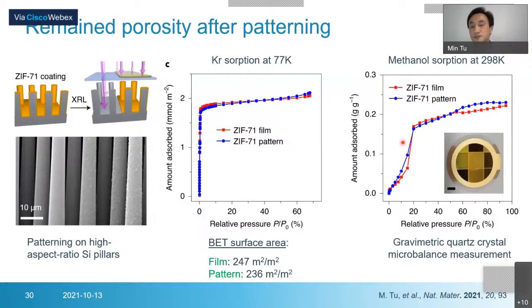We can also do methanol adsorption on quartz crystal microbalances, kind of a gravimetric measurement. We have a film coated on the surface, introduce methanol, monitor the frequency change, and calculate the mass change. Before and after the patterning, we measured the methanol uptake, and we can see kind of similar adsorption isotherms, both the shape and the quantity. So with both of these measurements, we can confirm that after X-ray or e-beam lithography, we remain our porosity.